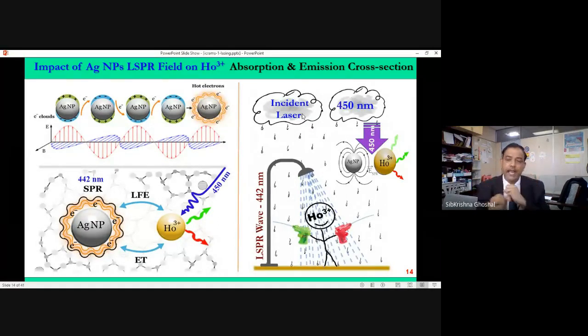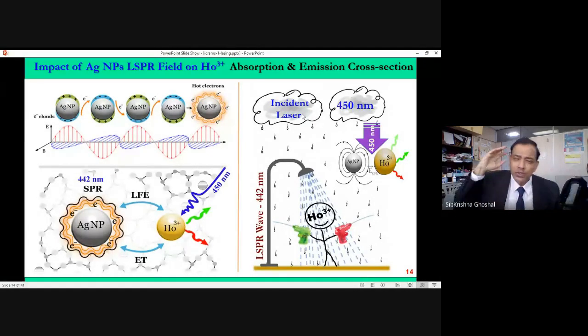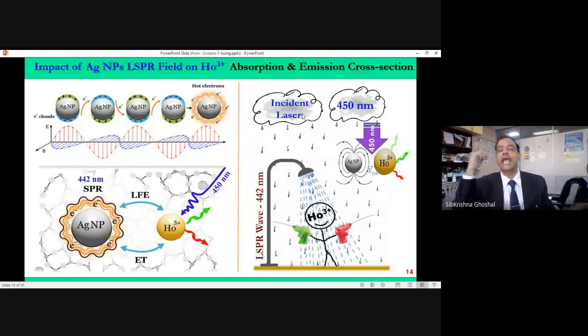And if we can tune this synergy, if we can control this synergy, how can we control this synergy? We have to choose the right composition of the glass ceramic. Remember, the moment you form the crystal lattice or the amorphous material, they have a lot of bonds. So they have a lot of molecular phonons. This molecular phonon will eat the photon faster than the holmium. So how to tune that complex game?